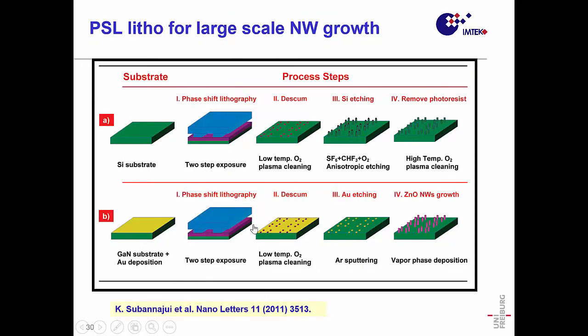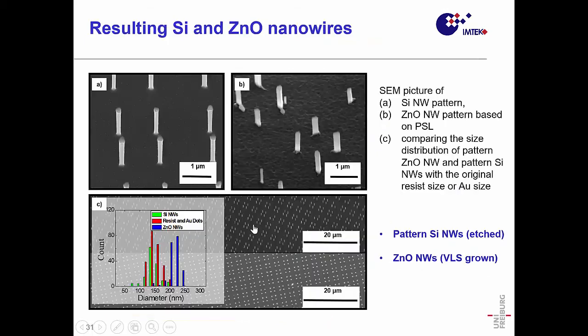We did that in two ways. We did that for etching. We did that for growth of the nanowire. I show you two of the examples. I don't want to go into the details here. One is a silicon etched and one is grown of zinc oxide. What you're seeing is it can be done on growth on large scale.